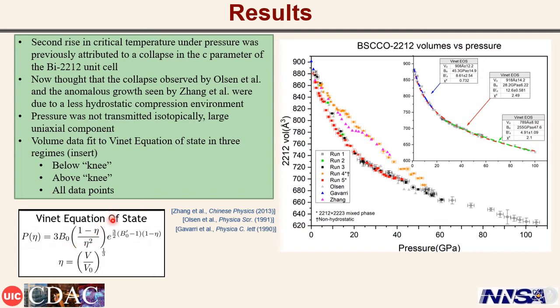There appears to be an isostructural phase transition where the bulk modulus dramatically increases, corresponding to a stiffening of the C parameter. This is reflected in the knee seen in the unit cell volumes around 20 gigapascals. The fact that the dramatic increase in Tc occurs irrespective of the pressure transmitting medium implies that whatever mechanism is responsible for superconductivity in the cuprates effectively ignores any collapse due to non-hydrostatic stress.